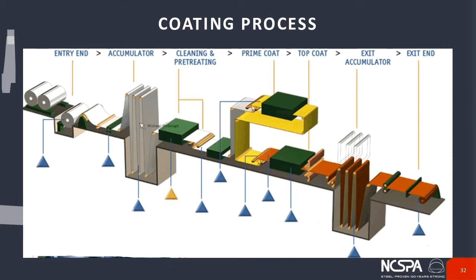So busy slide here, but on the far left, we start off with those galvanized coils, and it goes through a process. I'm not going to worry about explaining what an accumulator is, but the coil is cleaned and scrubbed. When galvanized coil comes from the mill, if you don't call it out not to have it, it comes with a zinc chromate coating on it. It's kind of a waxy coating, so that coating, if it's on there, is scrubbed off in an acid bath, cleaned up, and then it's prime coated. The coating is applied under pressure, and then it goes through a heater, sets it, goes out the other end, and you end up with a polymer coated coil over here on the right.